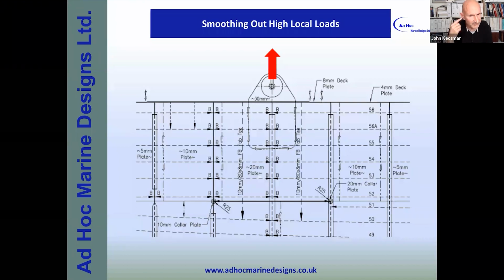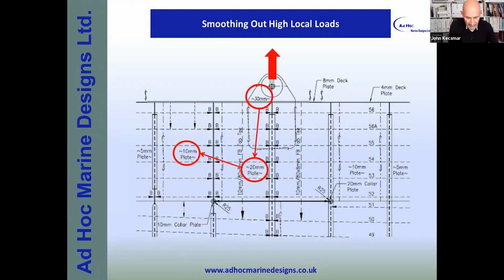And by way of a very simple example, here is a lifting lug, and it has a very, very high concentrated load. So just like changing the stiffness, how do I change the load so it's going to be distributed nice and smoothly? Because when we see that we're going from a 30mm plate down to 5mm, we can't really just butt the 5mm into the 30. That's quite ludicrous. So what we have to do is calculate the available shear area in both the weld length and the amount of metal you have, and then doing so, transfer down to 20mm plate, and then again down to 10mm plate, and then of course eventually down to 5mm plate. So simple things like this are quite important, yet quite often they're overlooked.